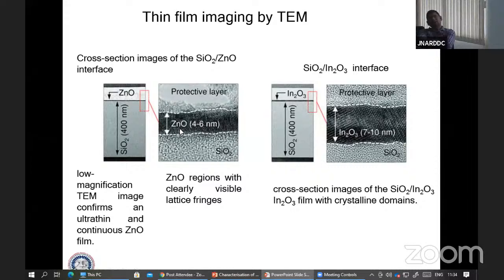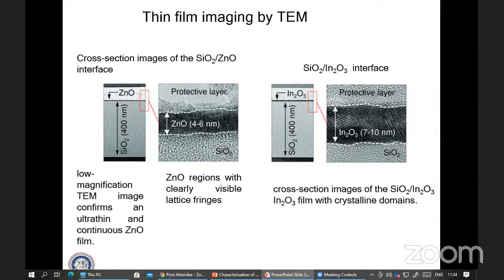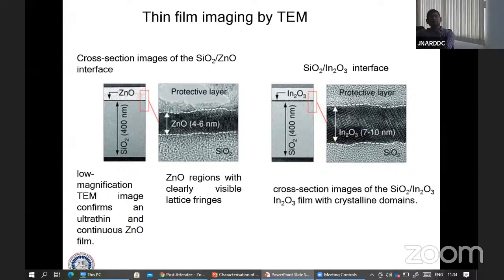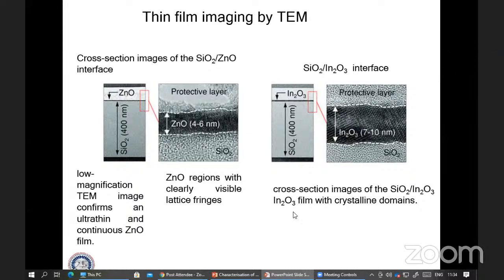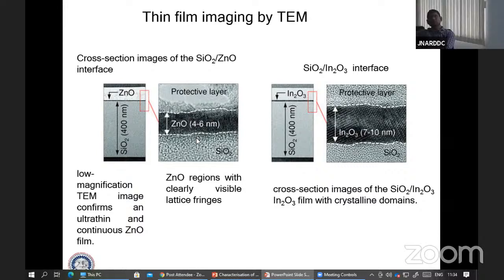So as I said, the preparation of these cross-sectional image samples, and this is the imaging of the cross-section or thin film samples by transmission electron microscope. You can also measure your zinc oxide thickness here, 4 to 6 nanometers. And the rest is silica. And suppose you have a silica with indium oxide interface, so you can also measure the thin film thickness under the transmission electron microscope.